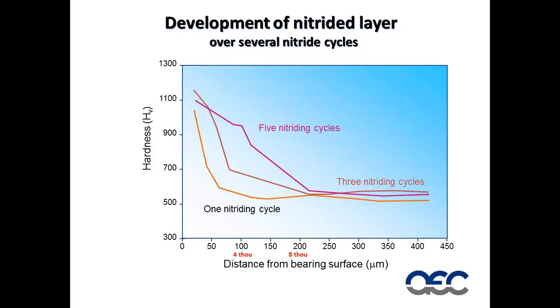Now, people often ask me, how often should I nitride a die? Well, obviously you need to nitride it at the beginning, but what you get is this first nitriding layer. And this is actually quite a fine, delicate layer. So our first period before we do our next nitriding should be relatively short. And as we get on towards 3 to 5 layers, we can extend out our period between nitriding cycles.